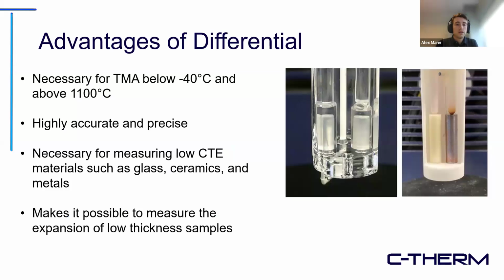So what are the advantages of a differential method? In my opinion, differential TMA is necessary for very low temperatures and very high temperatures. The CTE tends to increase with temperature, so at very, very low temperatures there's not very much expansion. And when there's very little expansion, you really need to be accurate and precise to avoid large errors. This is why it's important below -40.